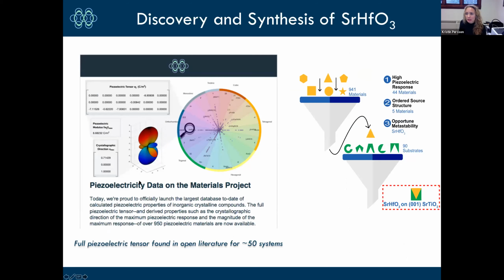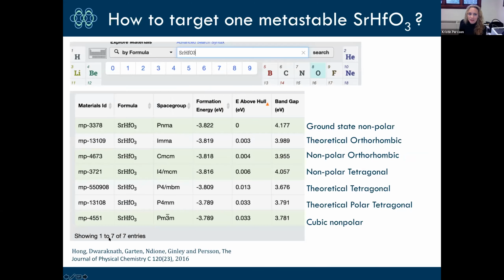So in this case, we were again looking for a material with a high piezoelectric response that did not contain lead. And we had some very fearless collaborators at NREL, one of our national laboratories here in the US, who were interested in seeing if we could make a material that had never been made before. Their interest was not just in the piezoelectric part, but also in the synthesis aspect of the challenge. So instead of taking one of the more low-hanging fruit, the materials that have been made, we took a material that had never been made before. This was a distorted perovskite, a strontium hafnium oxide. And I'll tell you why this was a very challenging material to go after.